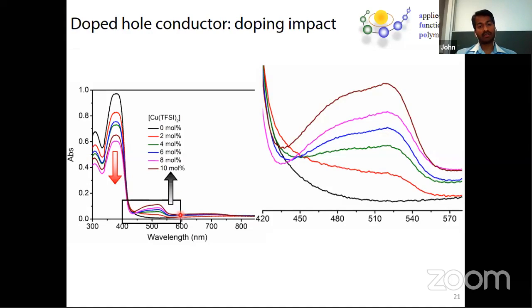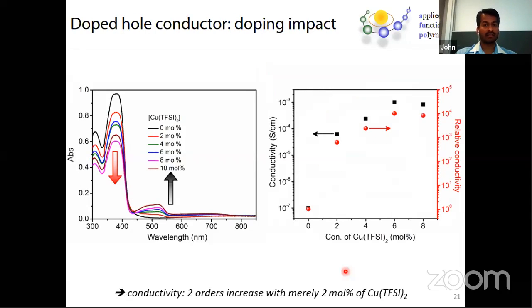So again, we carried out a UV-vis absorption experiment, and we found a very similar peak as in the solution-based titration experiments, a new peak at around 520 nanometers. This once again confirms that even in the solid state, our dopant is able to p-dope, or positively dope, the spiro-MeOTAD. The important factor is, once again, the conductivity of the system. The idea of doping itself comes from here. It's about how much you are improving your conductivity by doping, or whether you are gaining or losing. So in our case, we characterized our material.